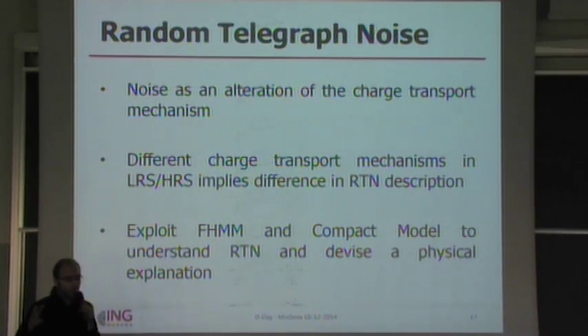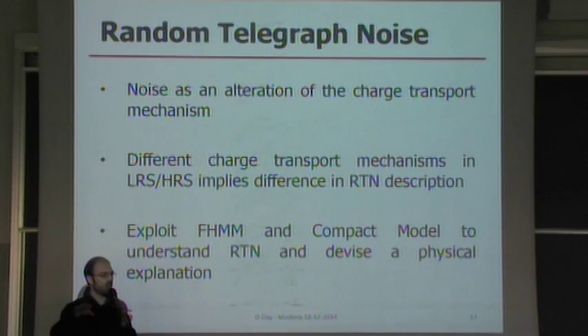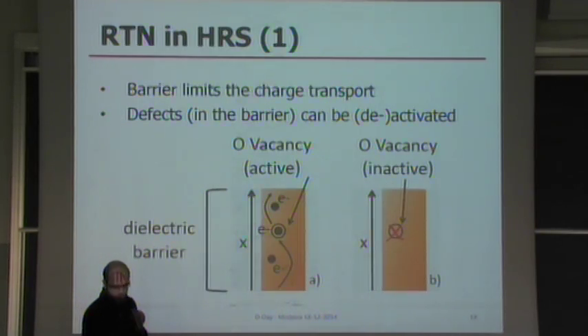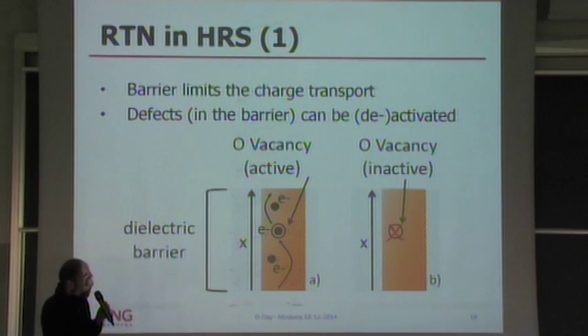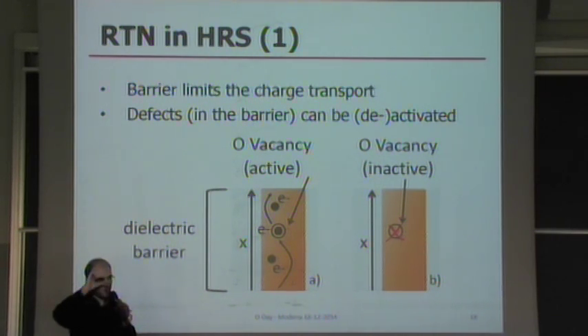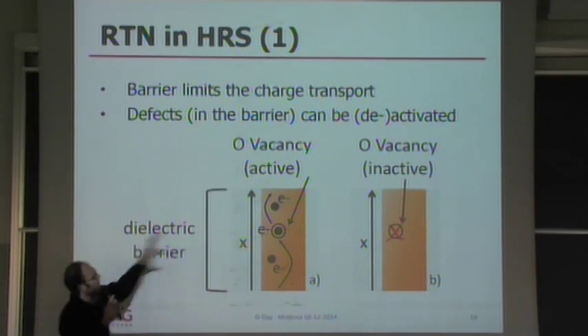But remember, we also have to deal with random telegraph noise. And random telegraph noise is just an alteration of the charge transport mechanism. So since we have two different charge transport mechanisms in the two resistive states, I have to separate the two things. So first of all, we're going to devise a model for the HRS RTN. Now, in HRS, I have to recall that we have a dielectric barrier, which is not present in LRS. We have the whole conductive filament. In HRS, we have this dielectric barrier, which is limiting the charge transport. So we are going to look directly at the barrier. This is not the whole device. This is only the barrier.